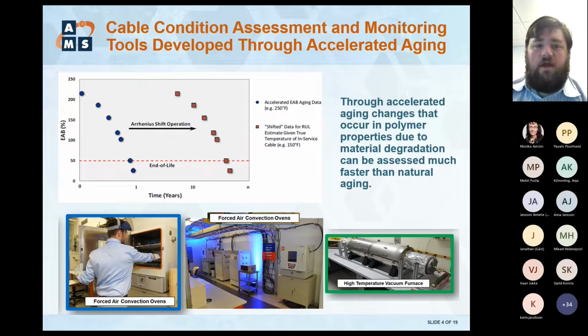So that's the kind of assumption that we make. Again, that has to be taken with a grain of salt, and I'll talk about that in the next couple of slides. But that's the general approach. We say that polymers, and in general, it's true over a fairly wide temperature range, follow time temperature superposition properties. A lot of the properties, especially mechanical properties, follow those relationships. And so again, we can use data taken at higher temperatures or higher levels of stress, and use that to reflect service environment degradation. And so that's what we actually employ for condition monitoring tool development generally.